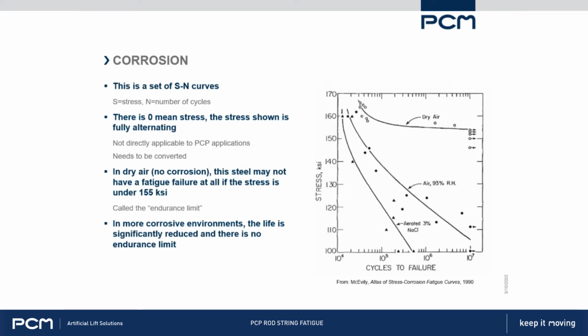And in a PCP application, if you're running at 200 RPM, for example, 10 million cycles is about a month. So just because it hasn't failed in 10 million doesn't mean it's not going to fail. Because even if you've got a fairly benign environment, there's water in most wells, a little bit of CO2 perhaps, you're going to have some corrosion. So it's likely this is not an endurance limit we're seeing here, but just that we haven't reached failure yet.